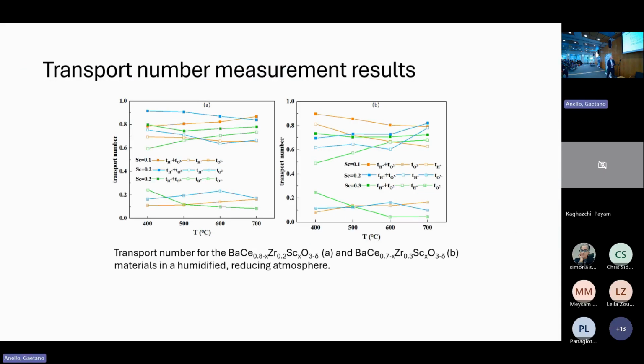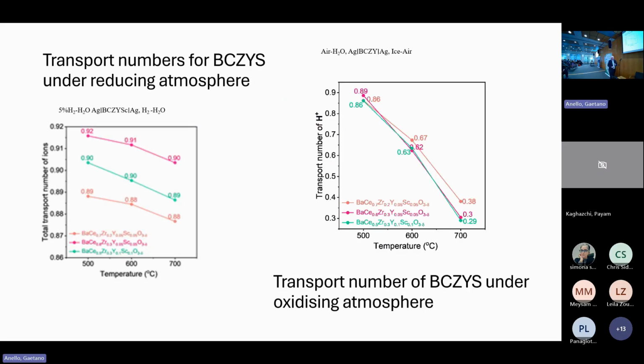So the materials we're looking at here, these are proton transport numbers, about 80% in reducing conditions. Oxygen transport, the best samples are giving us about 20%. So a 4-to-1 ratio is quite acceptable. So in reducing conditions, total transport number is quite high. Under oxidizing conditions, you get more hole conductivity. So you can lose quite a lot of conductivity under oxidizing conditions. So you have protons, you have oxygens, and holes. So you don't want to go to too high a temperature in this situation.